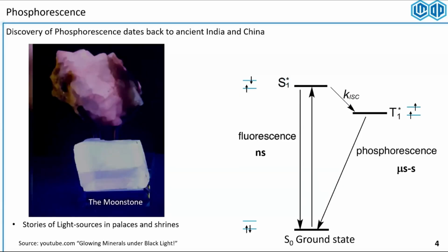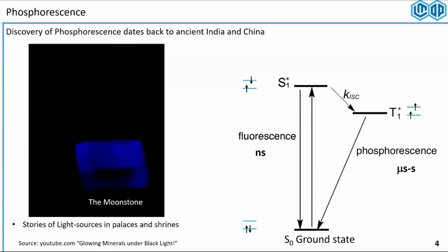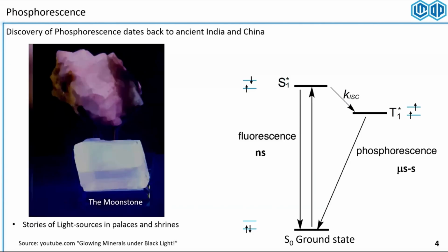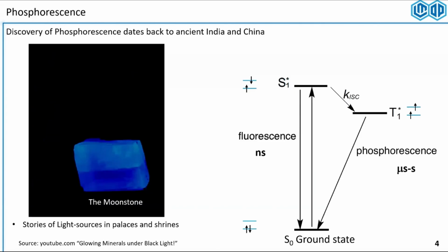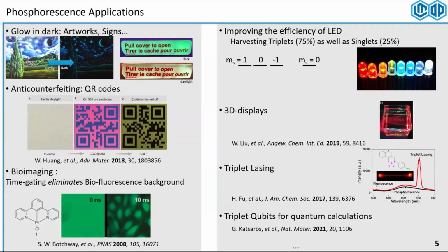And the main difference essentially, the most important characteristic difference of fluorescence and phosphorescence is the spin of the two excited states, and the lifetime at which they are going to emit, right? One being spontaneous, one being in microsecond to second regimes. And these two characteristics brought a lot of applications. Of course, we want to see afterglow for glow in the dark toys and artworks, and you probably have seen it on the planes. When it gets dark, you see all these notices starting to glow at night. And for anti-counterfeiting, for bioimaging, where you can have fluorescence background gone, and phosphorescence code or the stain systems start to show up. But also the triplet manifold allows us to harvest more excitons from our LEDs and conventional LEDs.